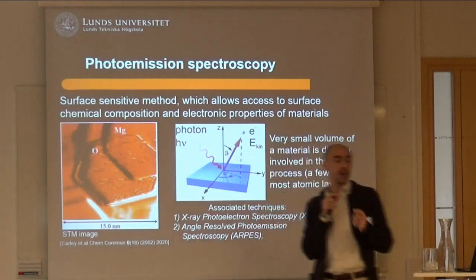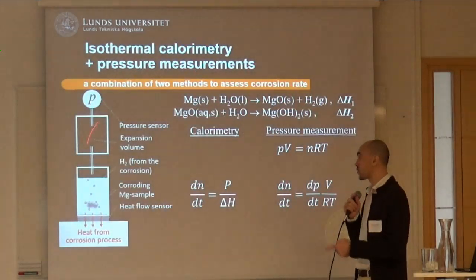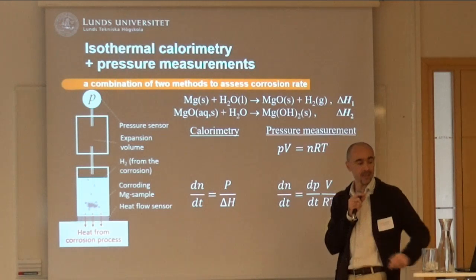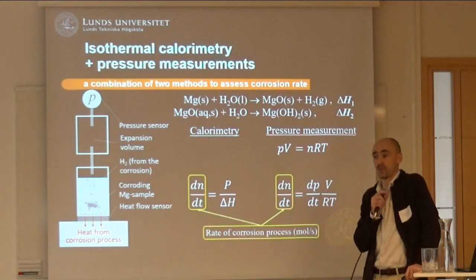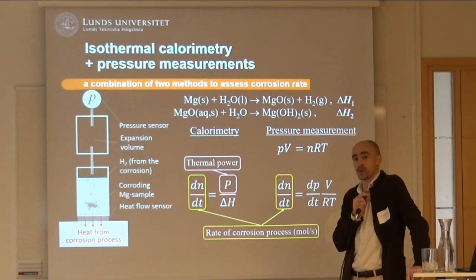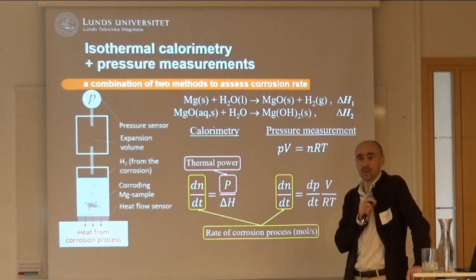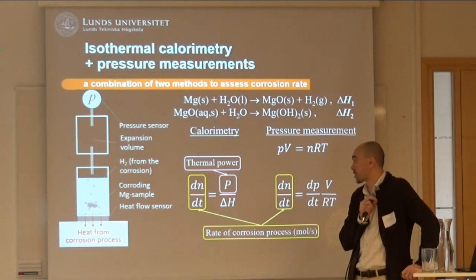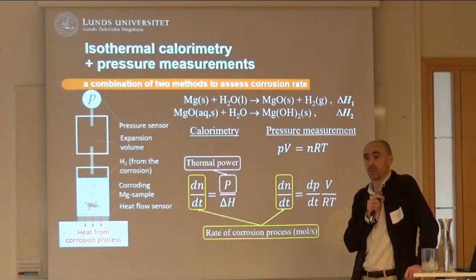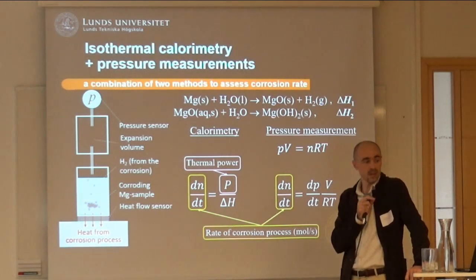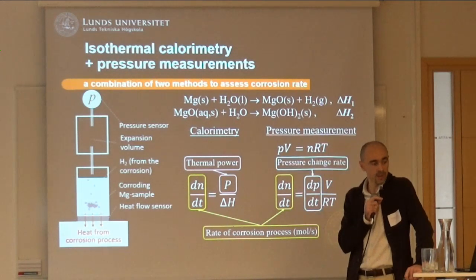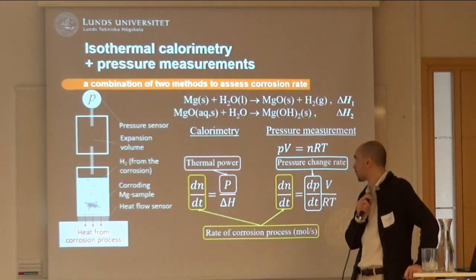But then we developed an in-house facility for magnesium oxidation in aqueous environment, and from that we come much closer to real-life applications. In the synchrotron, it is still very much a staged experiment. In the lab, we have just real-life alloy, real-life fluid, so we can do it in a bulk state, and we can analyze every stage of magnesium corrosion and oxidation.